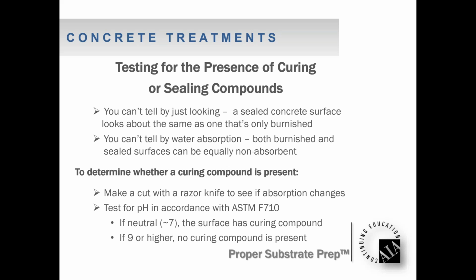The other thing you can do is do a pH test in accordance with ASTM F710. If we do a pH test on regular concrete, we're going to see a pH of 9, 10, because that's the common pH of concrete that has been poured, allowed to cure and dry as that surface carbonates a little bit. We get a pH around a 9 or a 10. If you have a sealer of any sort on there, whether it's a cure and seal, an acrylic, an epoxy or urethane, and you do a pH test on that surface, you're most likely going to get a neutral reading because the cure and seal, the sealer, whatever's there has a neutral reading. And if you get that neutral reading, that's telling you that there's something on the surface of that concrete.